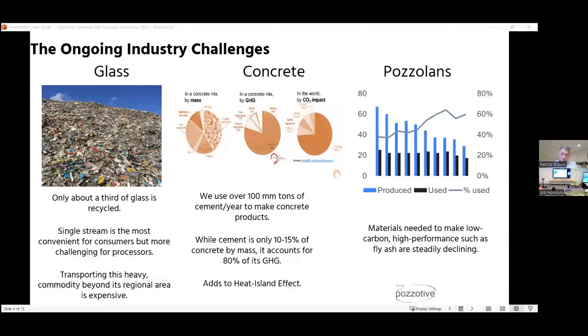The concrete industry, you've all probably been talking about a lot. Nationally, we use well over 100 million tons. I think the last recorded numbers are about 120 million tons or so of cement consumed in the U.S. While cement only makes up 10 to 15% by mass of concrete, it's about 80% of the carbon footprint. So that's what you want to attack and replace to get that carbon footprint of concrete down.